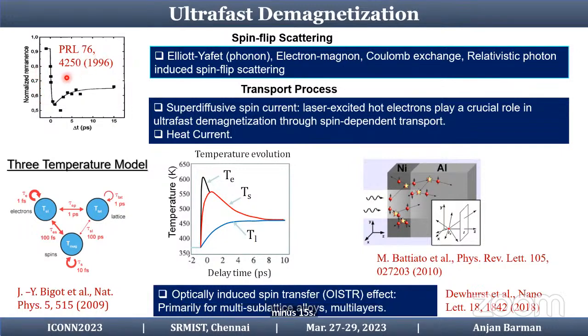And you can see the first work on this was reported in 1996 when Beaurepaire et al. showed that a magnetic material, nickel, can be partially or fully demagnetized by shining with a laser light, and that laser is a femtosecond laser, and then it follows a recovery. And they used the phenomenological three temperature model consisting of three different baths, the electron, lattice, and spin bath, which couple with each other and interact. And since then, it has gained a lot of momentum, and there have been many theories which try to explain this. And one of those is basically the spin flip scattering process.